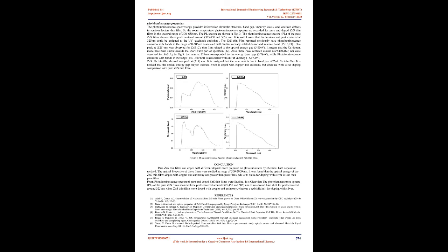The photoluminescence spectra, PL, of the pure ZnS films showed 3 peaks centered around 325, 450 and 505 nm. It is well known that the luminescent peak centered at 325 nm could be assigned to the UV excitonic emission. The ZnS thin films reported previously have photoluminescence emission with bands in the range 450-505 nm associated with sulfur vacancy-related donor and valence band 15, 16, 21. One peak at 323 nm was observed for ZnS:Cu thin film, related to the optical energy gap, 3.85 eV. It means that the Cu dopant made blue band shifts towards the short-wave part of the spectrum 22.